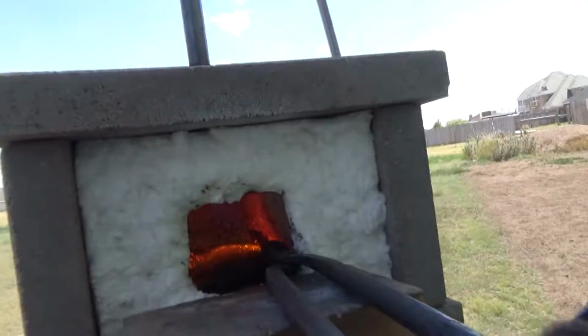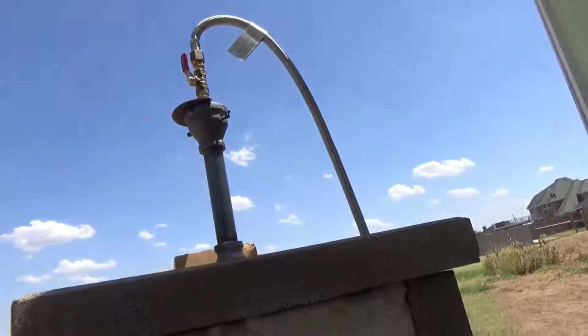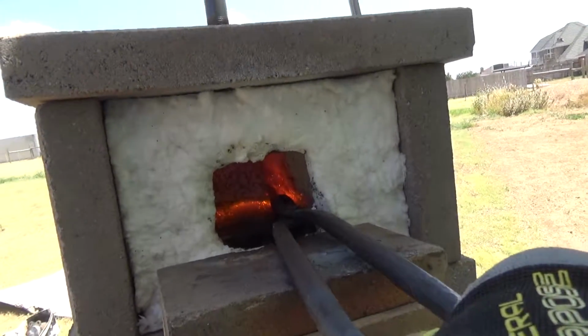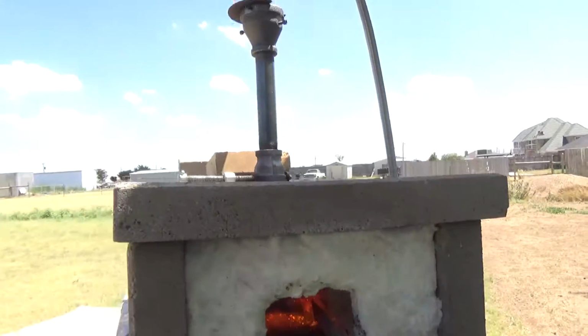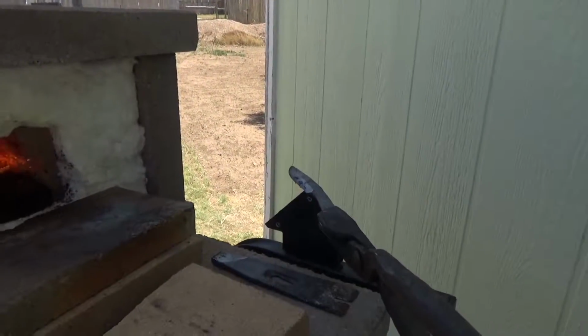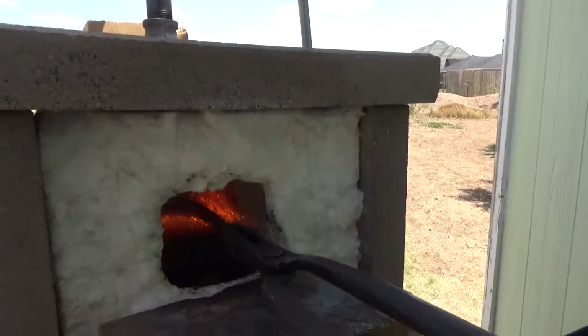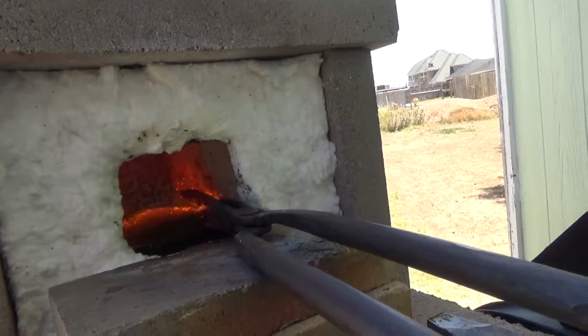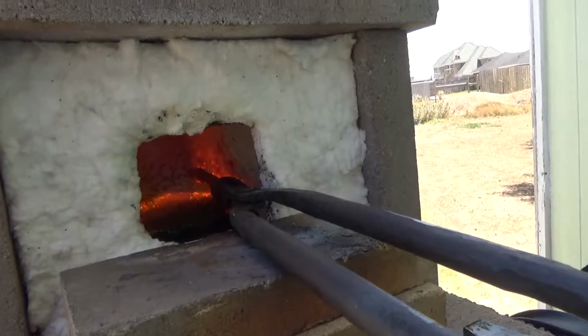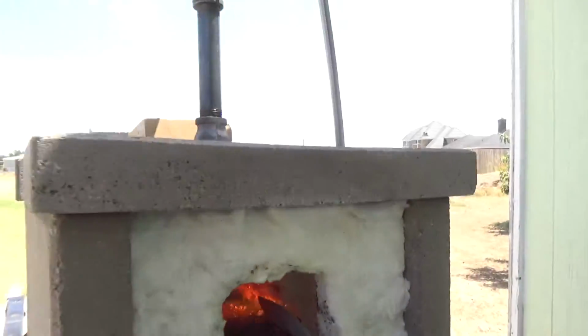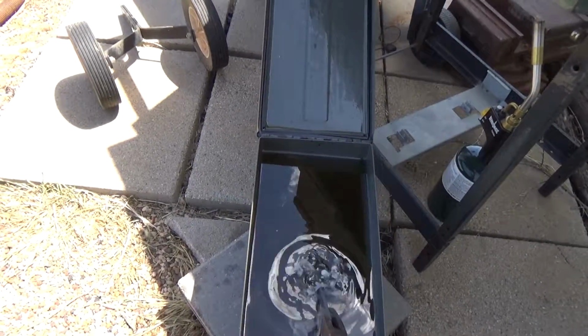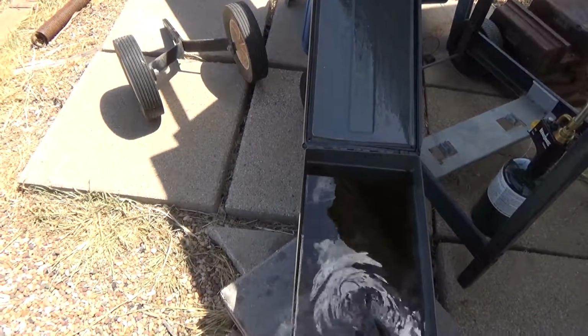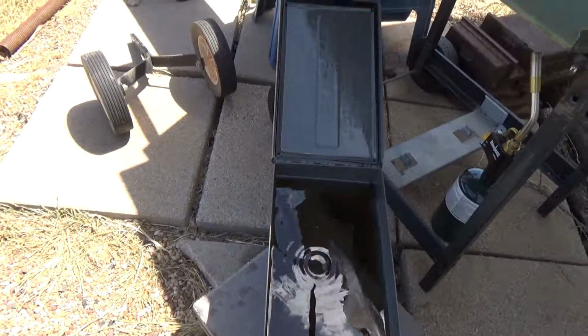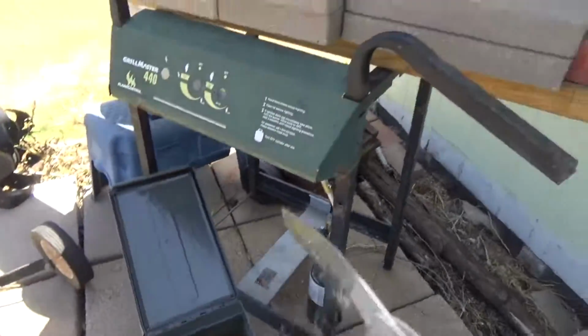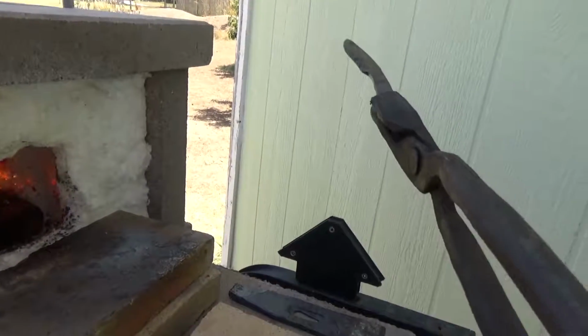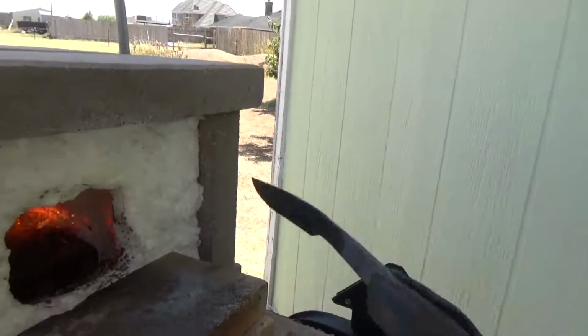So I've got it in the forge, getting it up to temperature. I'm seeing that it's glowing, and so I pull it out and I check it against the magnet to make sure all of the material that I want to be non-magnetic is, which includes the ricasso and just slightly beyond into the handle. Once it's all non-magnetic, I'll put it back in the forge for a few seconds, and then I'll quench it, because I want to make sure that it has even heat and that it is all at that temperature. In the time it takes to pull the steel out and test it on the magnet and then put it down into the quench, it will lose some heat.